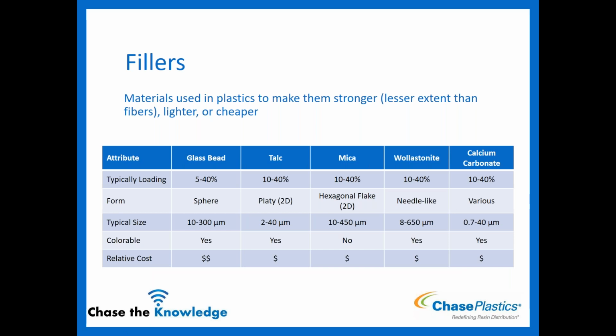So next we'll talk about fillers a little bit. We talked about the different mineral ones and then the glass bead ones. Similar concept, I give the size and the shape. If you look at the form, it has more of a 2D form or a sphere form, so it doesn't have that aspect ratio like your glass does. It's not a long fiber. But standard loading for these, anywhere from 5 to 40% is really common that you'll see.